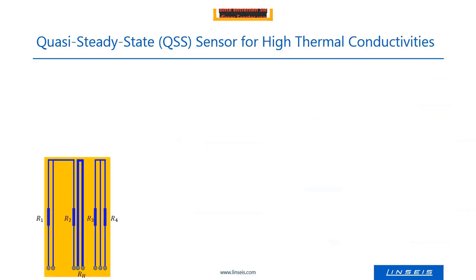To measure higher thermal conductivities, we use the so-called quasi-steady-state sensors, QSS sensors. With these sensors, we eliminate the time constant. So the setup of the sensor is a little bit different. We have a heater here in the middle. That's the heater. Then we have a thermometer, a PT100, at this position, and a second one, which has a bigger distance to the heater.